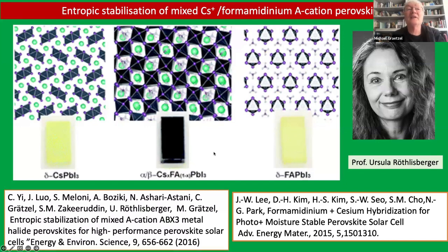And you see that very clearly here. They start with the yellow phase of both compounds; at room temperature the yellow phase is more stable. But when you mix them in a mortar, you can do a mechanochemical synthesis. We pioneered that with Professor Lewinsky from Warsaw. If you mix those in a mortar, it turns black. And so that's a magic way. Today's preferred formulations are these combinations: the cesium, say 5%, and the rest is formamidinium. These are certainly the formulations that people use now in commercial